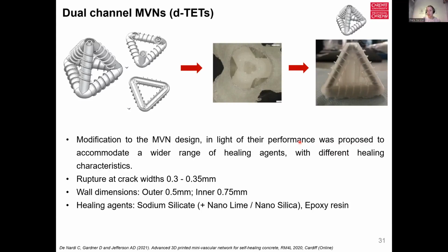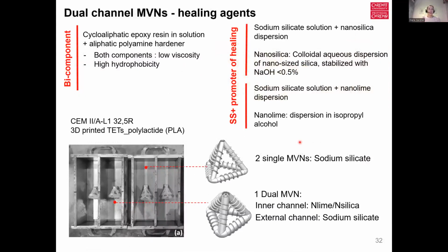The problem with bicomponents, so two component mixes, is that once they are in contact with each other, you get them reacting, and therefore we needed to make sure we satisfactorily separated them during the period of encapsulation. We looked at different healing agents, so sodium silicate and what we would call promoters of healing, and epoxy resins as well. So our epoxy resin was a two-part epoxy resin in solution. Both components had quite low viscosity but high hydrophobicity. And then our sodium silicate and our promoters of healing were our sodium silicate solution and nanosilica dispersion, and our sodium silicate solution with a nanolime dispersion. And both of these, especially the nanolime, was in an alcohol suspension.